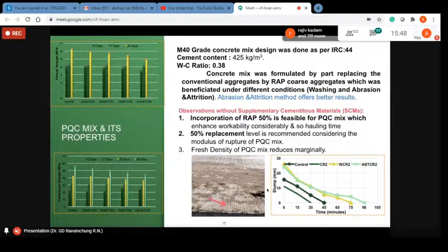Now in this context, what we have done is this 50% RAP percentage is fixed based on the flexural strength of the concrete. And also we have tried, why not? Because our attempt is to maximize the percentage replacement of natural aggregates by the RAP material or waste recycled aggregates, right? Since we have understood that by adopting abrasion and attrition techniques, we are getting better results for the concrete properties.